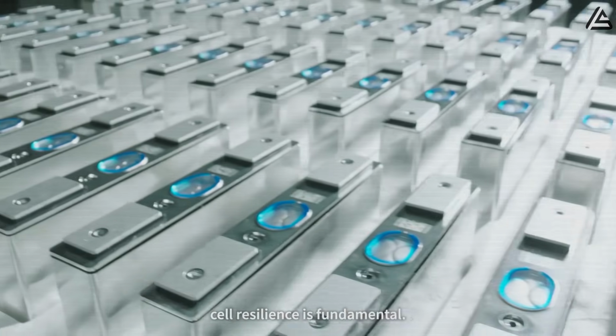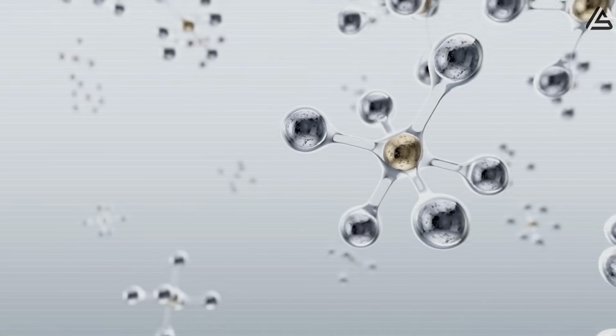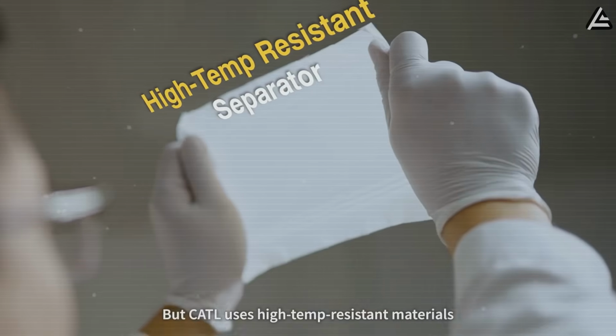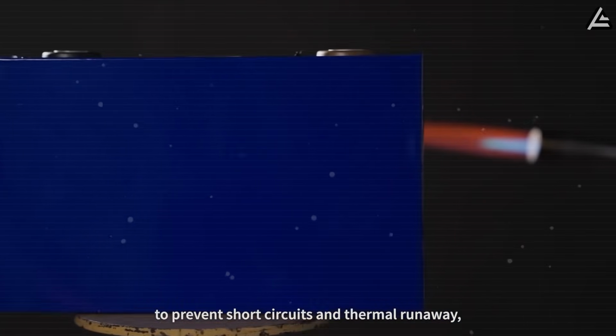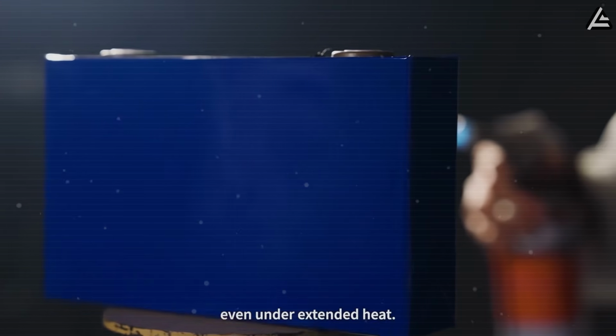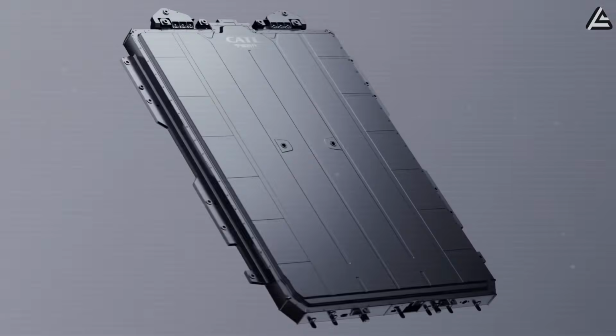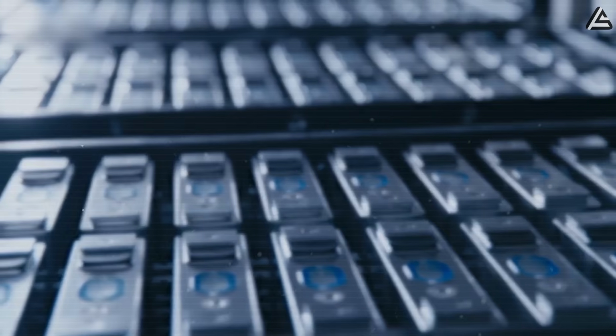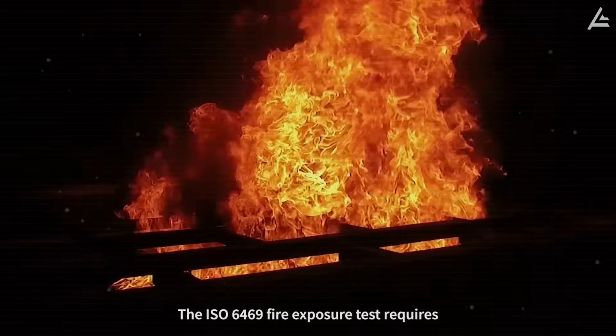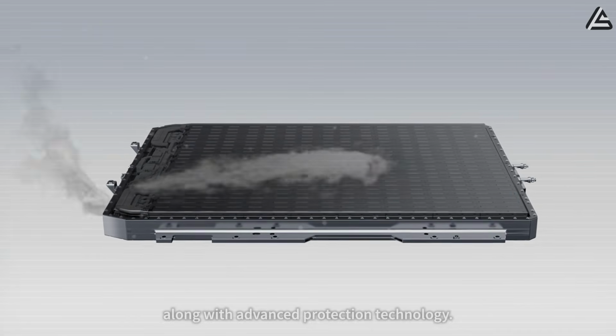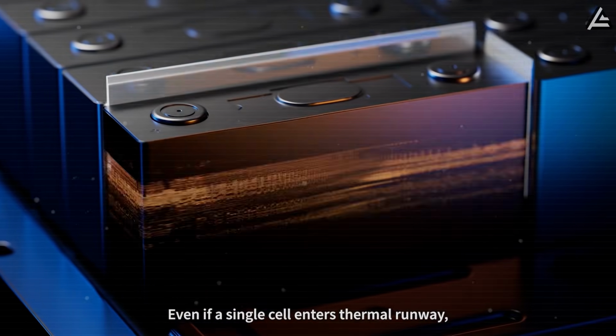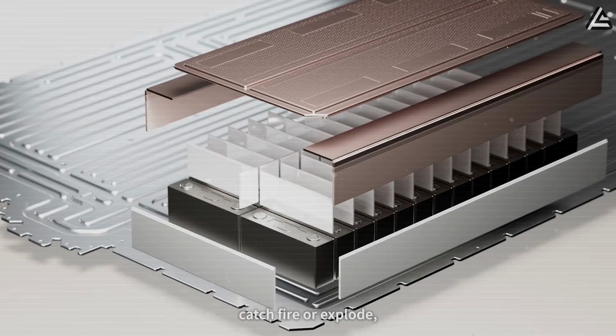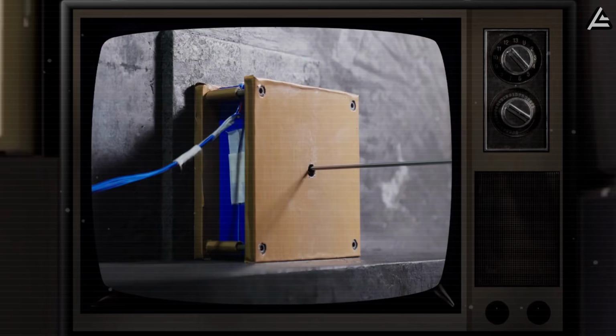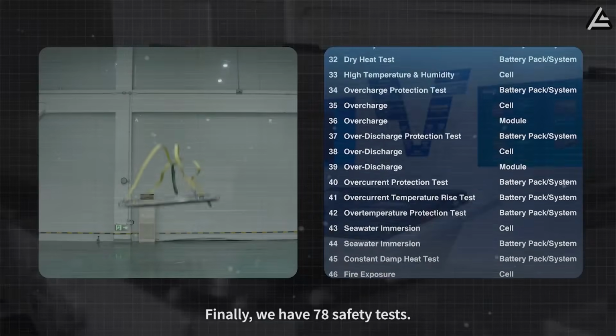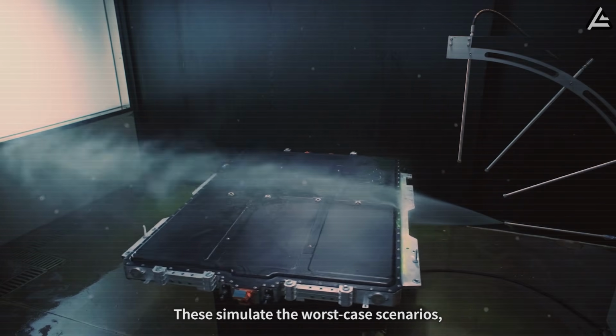By contrast, many sodium formulations under development incorporate higher stability solvents and additives designed to release less combustible gas under heat. Gas analysis during stress tests shows sodium-ion emitting significantly lower volumes of hydrogen and carbon monoxide, the fuels that typically feed an EV blaze. This does not eliminate risk altogether, but it sharply reduces the odds of flames jumping from one cell to another in a domino effect. Put together, these traits make sodium-ion harder to ignite, slower to escalate, and easier to contain if a fault occurs. For Tesla, that distinction is more than academic.